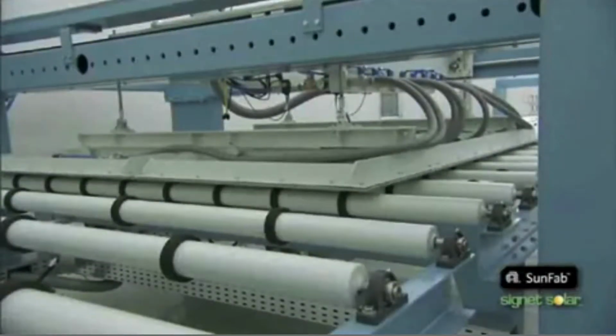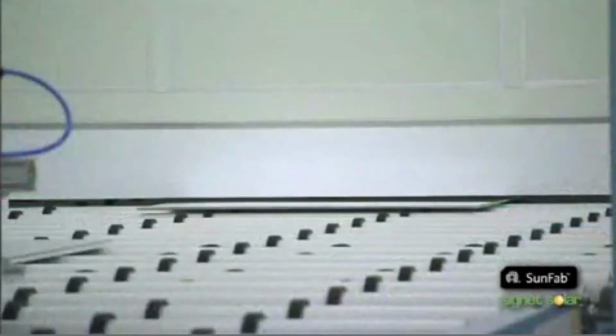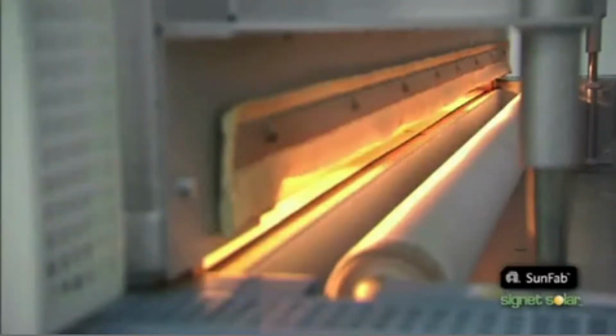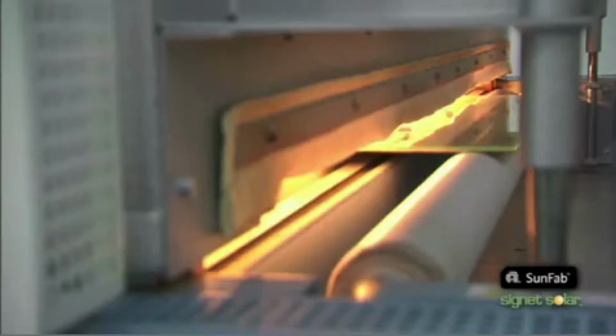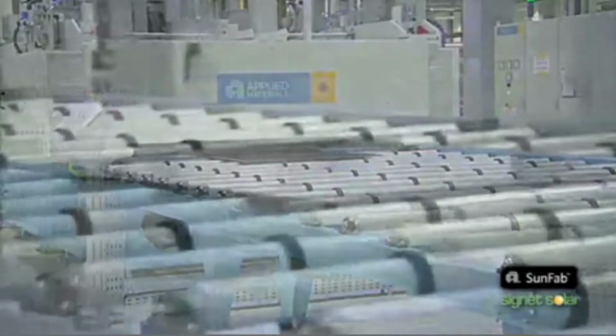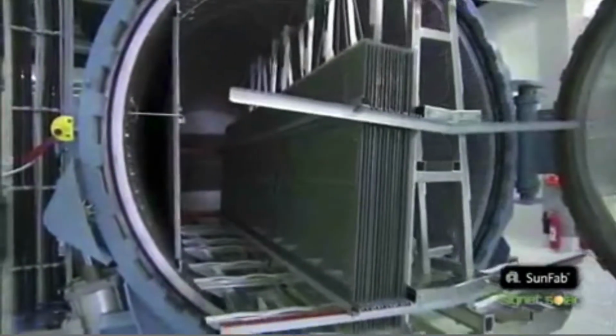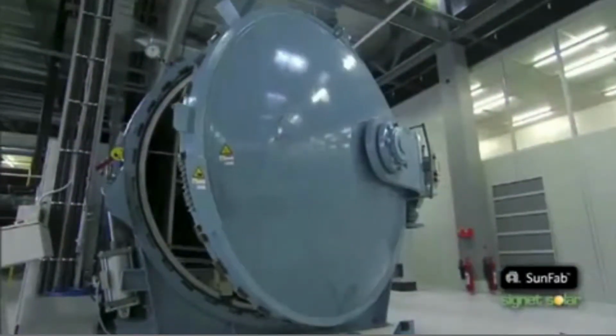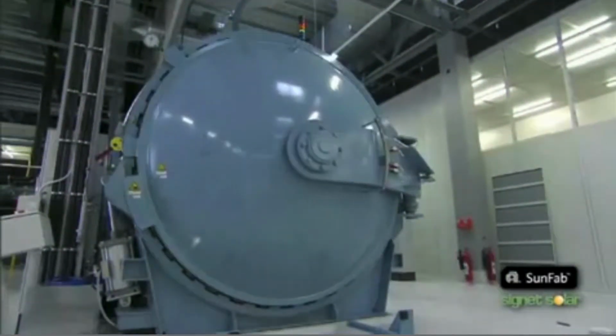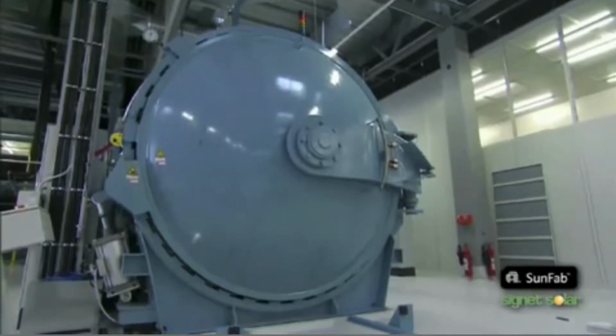Now, bus bars are added. The glass is now ready for lamination. A foil is cut to the right size and placed on the glass, followed by a sheet of back glass. The laminator spreads the foil out evenly between the front and back glass, thereby encapsulating the device. This makes it wind and water resistant. The module is then subjected to a high pressure, high temperature annealing process to remove trapped gases and create a good contact between the individual layers.